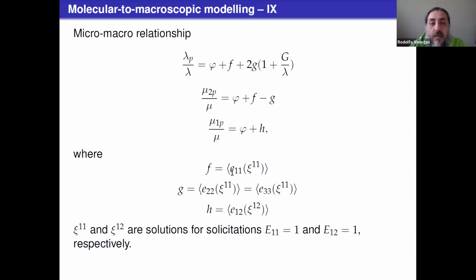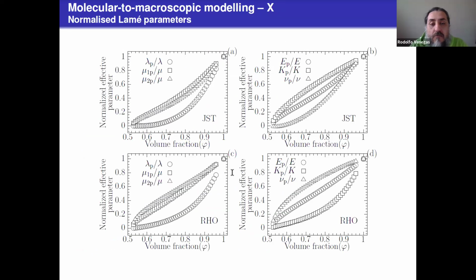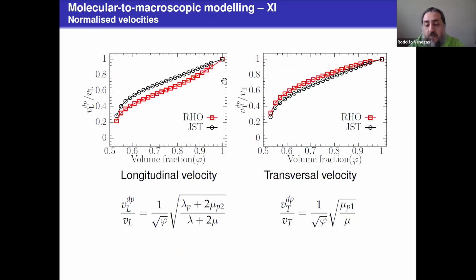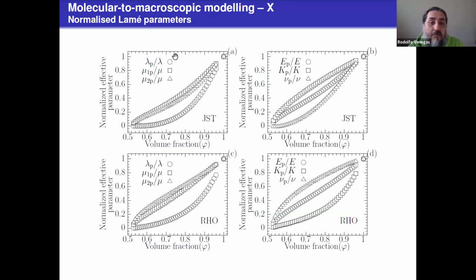this one. So in doing that, then we can work out the evolution of, for example, the Young modulus or the bulk modulus, or Poisson ratio with the volume fraction of the solid. They all show an increasing trend with increasing volume fraction, which makes a lot of sense, obviously, because if we have, for example, 100% of solid, then obviously this first Lamé parameter will be the first Lamé parameter of the substrate. So we have to get this value of 1.